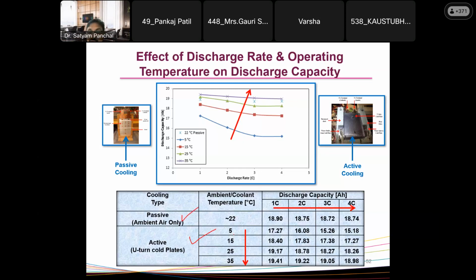corresponding for air cooling as well as for water cooling at 22 degrees, and then the amp hour discharge capacity. As I said earlier, this battery has 20 amp hour capacity. So 1C discharge means you will get close to 20 amp hour. But if you go at 2C, 3C, and 4C discharge, you will not get 20 amp hour. You will get around 18 amp hour. So you can see over here, even at 4C for air cooling, you are getting 18 amp hour.